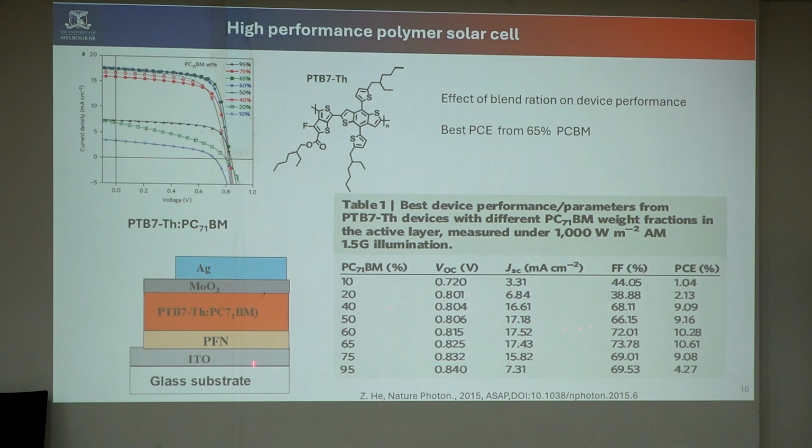With 65 meaning 65 percent, the remaining 35 is your donor material, around 1:1.5 or so. One portion is your donor and the remaining 1.5 is acceptor. In that ratio it works well.